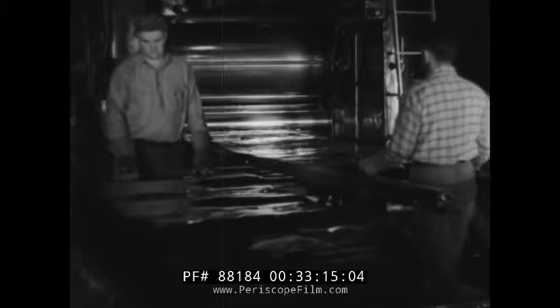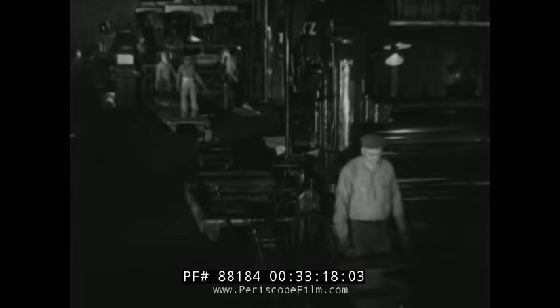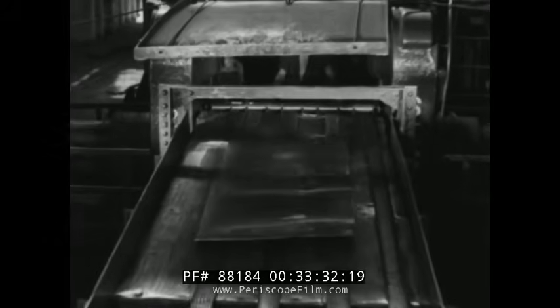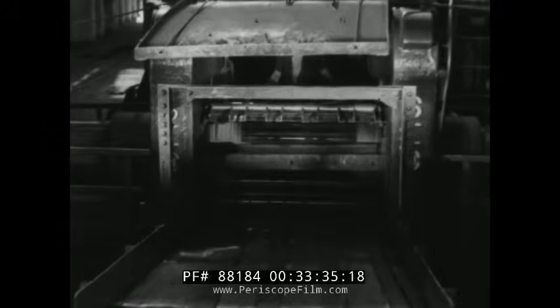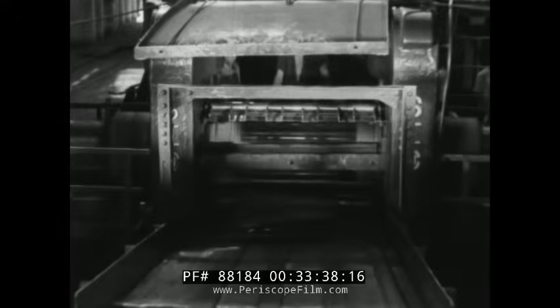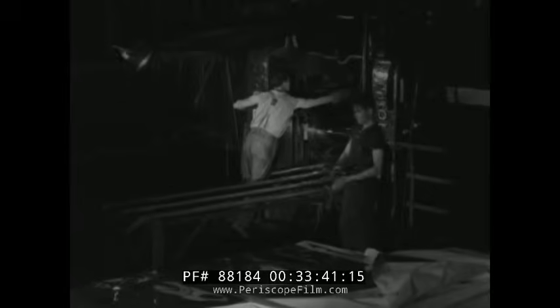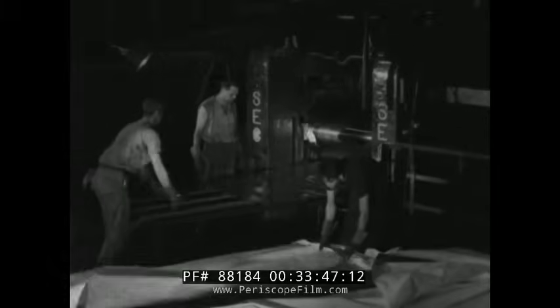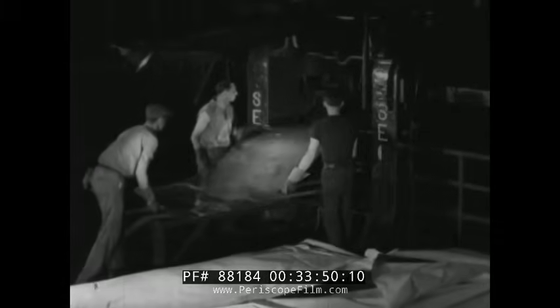In the cold rolling department, these high-pressure mills with carefully polished rolls burnish the surface of the sheets and add special physical properties which are required for certain industrial uses. Cold rolled sheets are flattened by a roller leveler machine. Standard 2-high cold mills are used where heavy reductions are not necessary. Through the mill over the top roll. Care must be taken to protect the surface of the sheet and preserve a uniform and accurate gauge. The highly finished sheet is covered with paper to protect it.